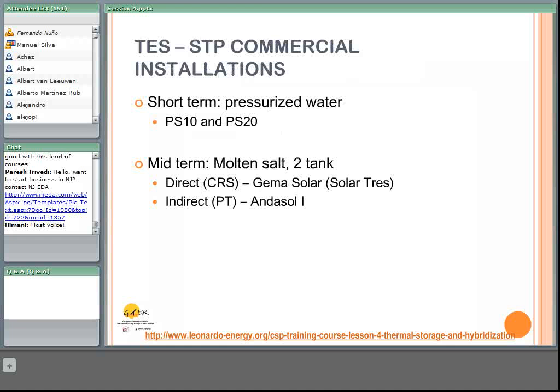This is Gemasolar, near Seville, which is the plant with such a large thermal storage system of 15 equivalent hours. And some plants, not only Andasol 1 but many other plants, are parabolic trough plants. They use an indirect thermal storage system with two tanks, also using molten salts as heat storage. The most representative, of course, is Andasol 1, because it has been the first plant to consider this concept, and now it's currently operating with this system.